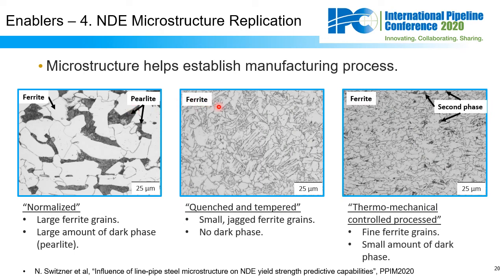Now in the middle, we have a microstructure produced by a more modern process, the quenching and tempering process for steelmaking, and we see small jagged grains and almost no dark phase. And on the right, we have a second microstructure produced by a relatively modern process called thermomechanical control processing for steelmaking, and we see fine ferrite grains and only a small amount of dark phase. So these are just some of the important differences that can be observed between microstructures for different manufacturing processes. Now next, let's take a look at our two case studies for vintage estimation.